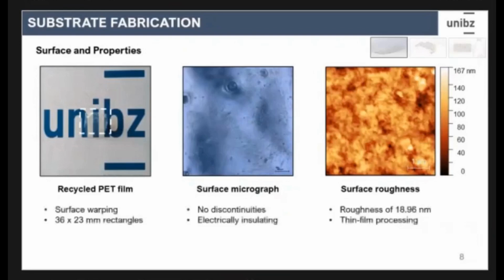So even though we found the surface warping, we created rectangles that were 36 by 23 millimeters in area. The surface didn't show any discontinuities. It was electrically insulating, keeping the same properties as rigid PET. And the roughness, as I said, was very small, around 18.96 nanometers, so perfect for thin-film processing.